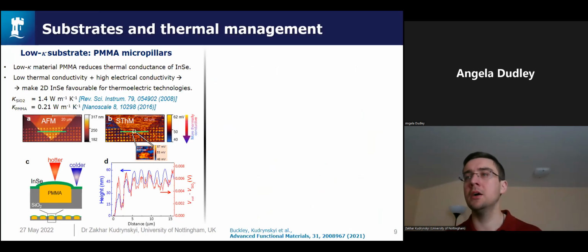The choice of the substrate often means to modulate the thermal response of a 2D material. We investigated indium selenide flakes on different substrates with low and high thermal conductivity. Here we transferred flakes on a periodic array of PMMA micropillars on a silicon dioxide substrate. PMMA has a very low thermal conductivity. We can see that our probe is getting hotter in the region where indium selenide is on PMMA than on indium selenide on silicon dioxide.